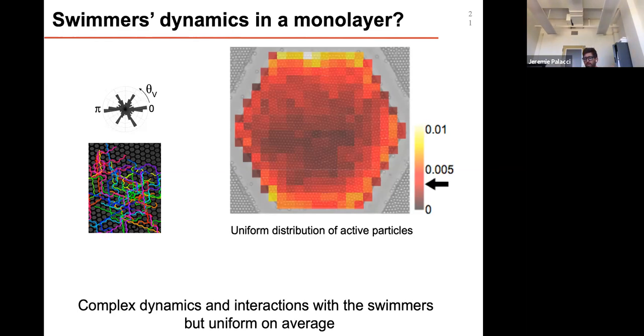It has been shown by Aparna and Michael Hagen at Brandeis and others that if you mix particles with different mobility or motility, you end up with a phase separation. So the active particles would push away the passive ones, and you would basically demix. As a consequence, your activity separates from your passive particles. In order to avoid this demixing, one thing you can do is to put boundaries, and then you confine your system to make sure that the active ones cannot push the passive ones.